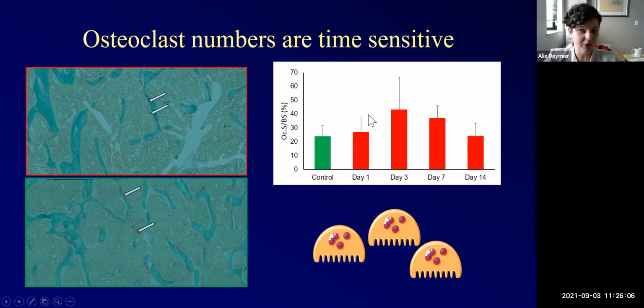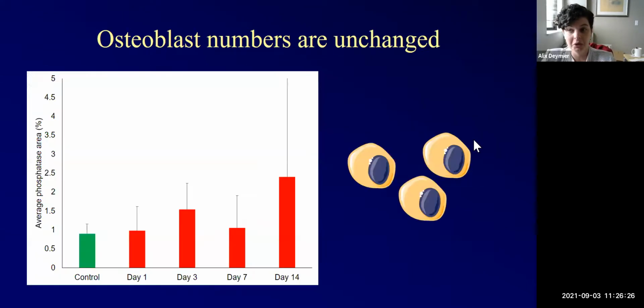So all those changes in the mineral composition and the organization of the mineral to matrix ratio and the structure of the bone, it's happening really fast. All happening in the middle here, and by day 14, you're already back to stable. So this was really interesting that we had this time dependence in bone resorption. So we thought, well, do we have it in bone formation? Nope. Bone formation is completely unaffected. So now we're starting to really get an understanding of how bone structure and material properties are probably playing a pretty important role, because the cell effects seem to be relatively temporary.